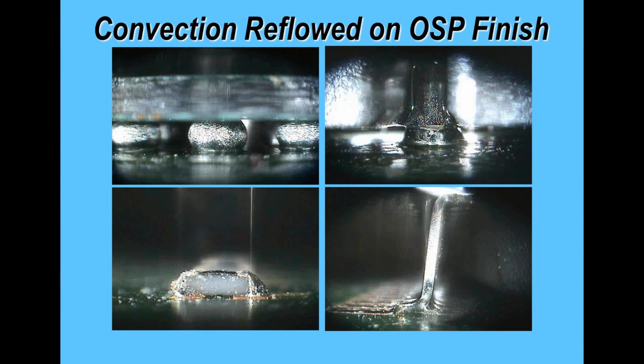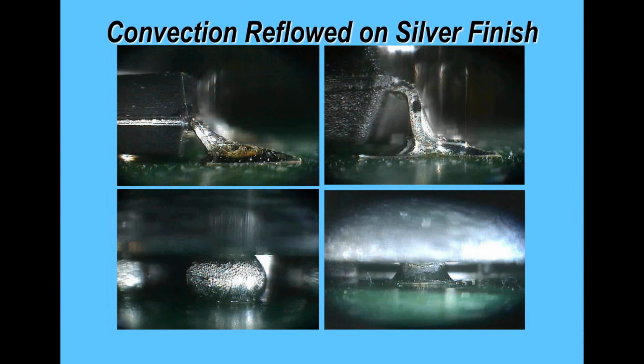Now if you're using OSP, you can normally see the edge of the pad. The solder doesn't tend to wet round the side, and if you're doing a microsection, you'd certainly see the same sort of impact on most terminations. Again, perfectly good joint. Here you see on a silver finish, again all the terminations I've previously shown, but you can't see any demarcation lines on the pad surface because it's the same color. The silver finish is, as its name suggests, silver in appearance, but all successful reflow solder joints with convection.